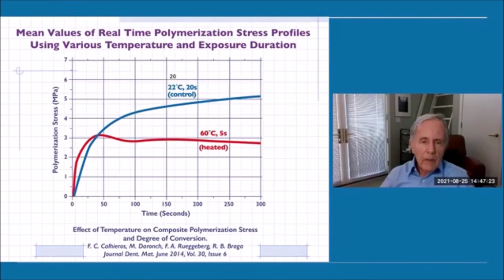What's happened in the material that was cured at room temperature is that it has a pretty high stress level, as you can see in the blue. The material that was heated, in the red, had much lower stress. So in effect, curing for 5 seconds gave us lower stress and higher monomer conversion. That's a combination that's almost too good to be true, but it is. And this is where that research is so important.